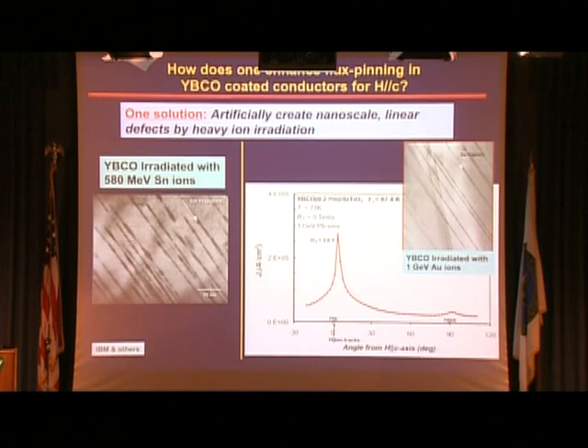They go through the single crystal, and as they go through the crystal, they amorphize wherever they go. They create these damaged tracks. So these tracks become non-superconducting. When you apply the magnetic field parallel to these tracks, you immobilize the lattice, and you get a big peak in the amount of current you can pass through the superconductor.